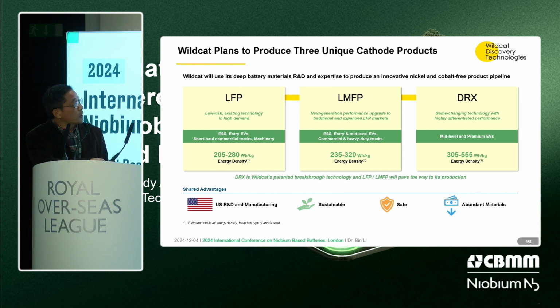Same thing, but if you look at all of the three, you can see DRX has much higher energy density at the cell level compared to LFP or LMFP. And also, it's even higher than the high nickel. And of course, the lithium metal still a little farther away. If you just look at the graphite, you still have the very high energy density.